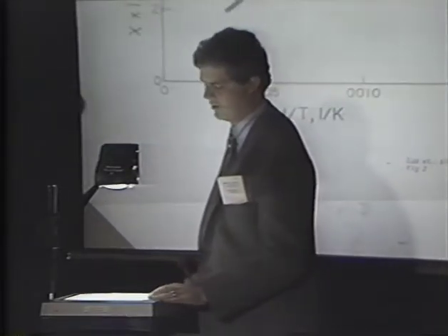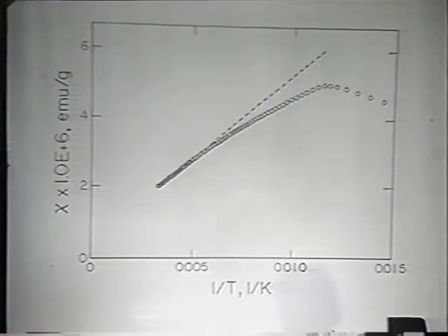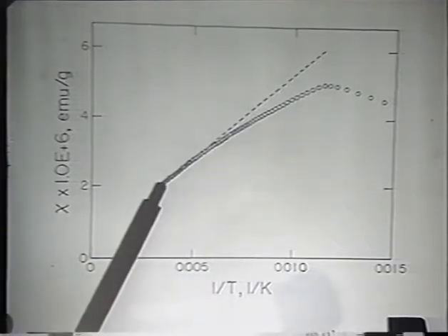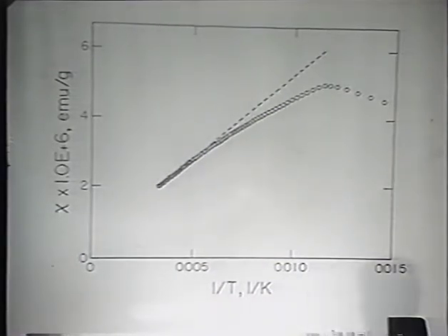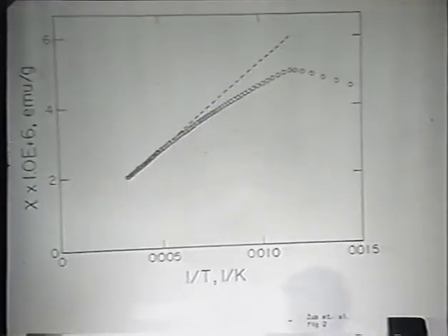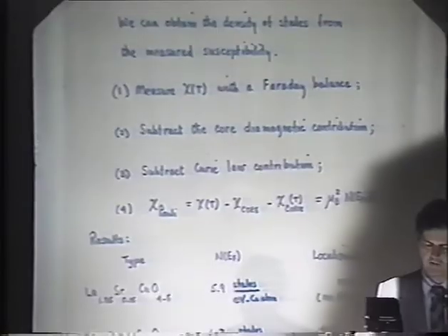Now, if we replot the yttrium susceptibility to really showcase the Curie law result, what you see is the susceptibility plotted against 1 over T is pretty accurately Curie law up near room temperature, these points, but then there are deviations as you get near the transition region. These deviations could be thought of as antiferromagnetic deviations, but that's certainly not the only possible explanation for those deviations.